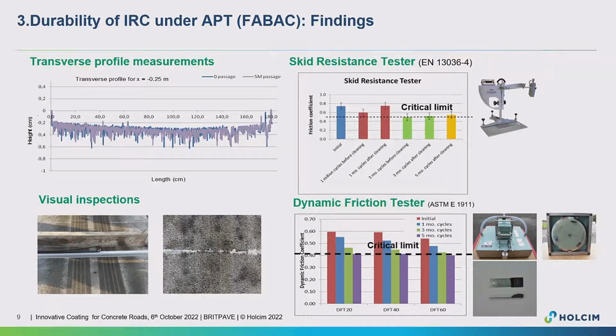With the skid resistance tester, the dynamic friction tester, we saw the evolution of the friction coefficient. But at the end of 5 million loading cycles, the value was still acceptable. So it means that maybe after 20 years, there's no issue in terms of safety or in terms of rutting, still on this solution under heavy traffic.